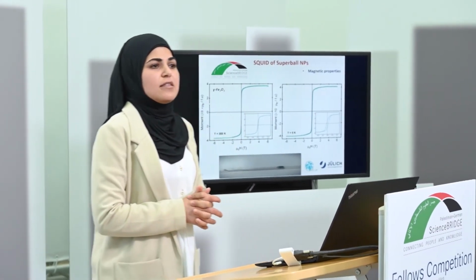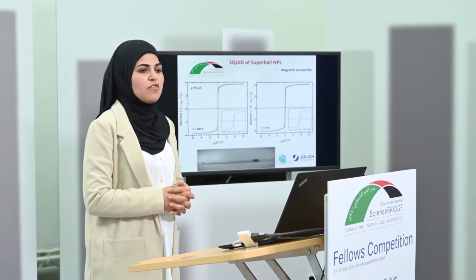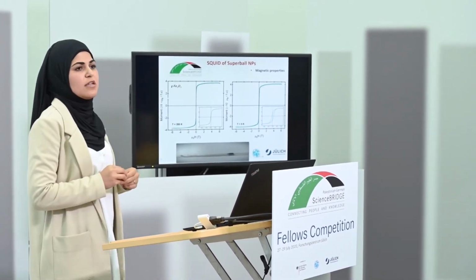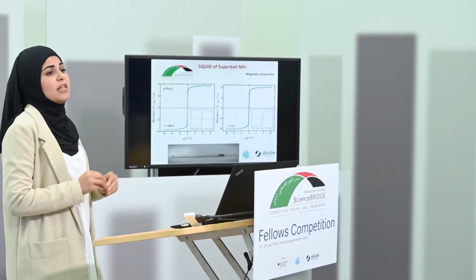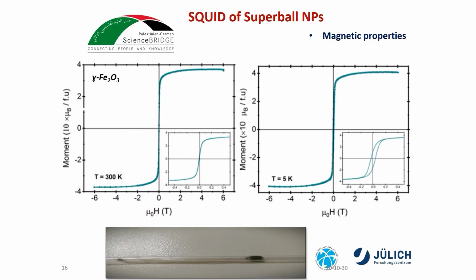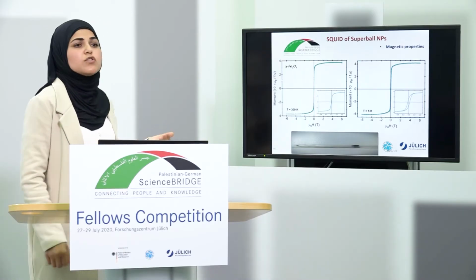To get information about the magnetic behavior of the nanoparticle, I'm showing here one example for the iron oxide nanoparticle. What's nice is that we can do a magnetization measurement for a liquid nanoparticle by filling the liquid inside a quartz ampoule, which is prepared at JCNS-2, and you can also measure at SQUID the magnetization as field dependent or temperature dependent.